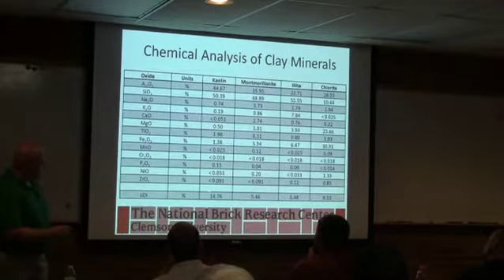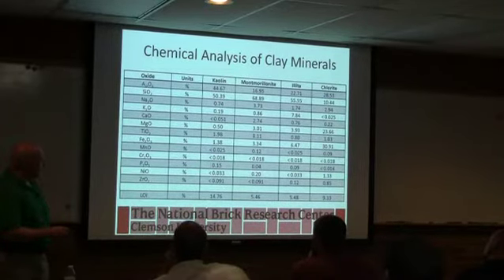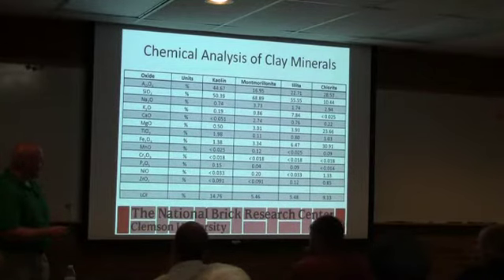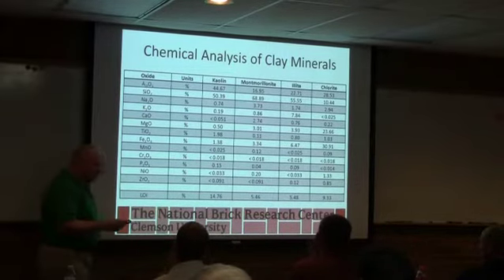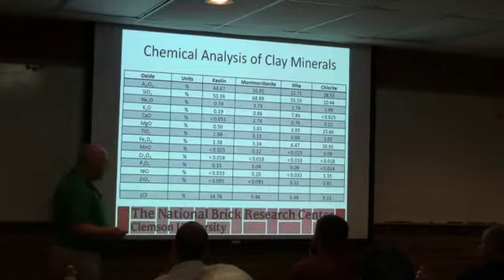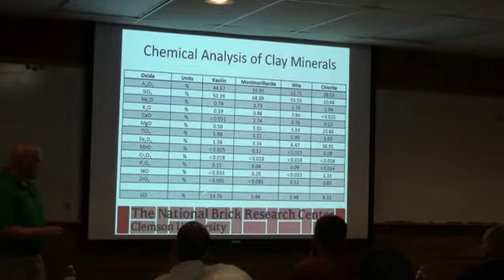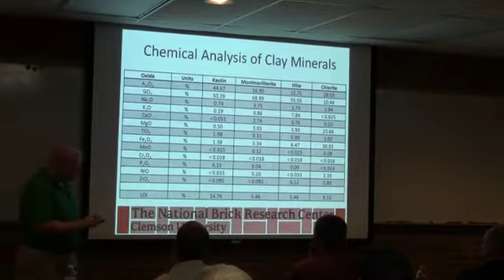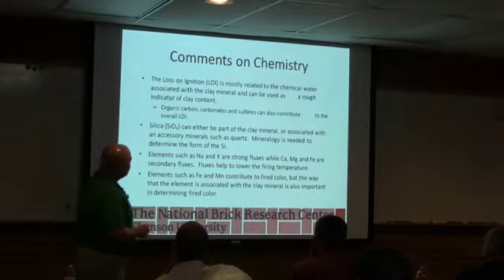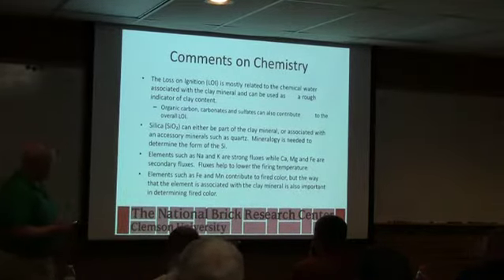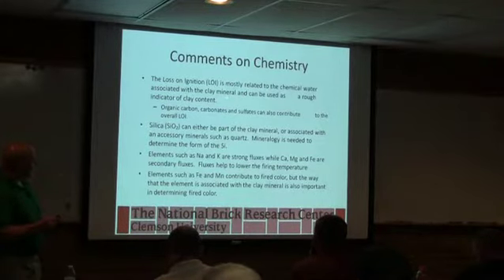Okay, so it takes a high temperature, whereas the montmorillonites and the illites are going to fire out at a much lower temperature. And remember I was telling you about the LOI? Okay, most of what I was telling you dealt with kaolinitic materials. But kaolin has a very high LOI, about 15% for pure kaolin. So usually the higher that number is in the raw material, and remember we were looking 6 to 8 in that previous chart, the higher that is, if it's a kaolinitic material, usually the more kaolin there is in it. So we use the LOI as a rough estimate of how much clay mineral.